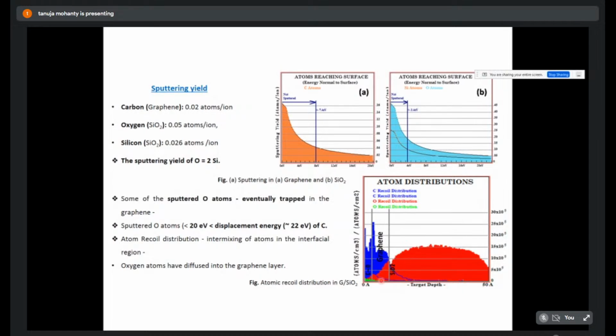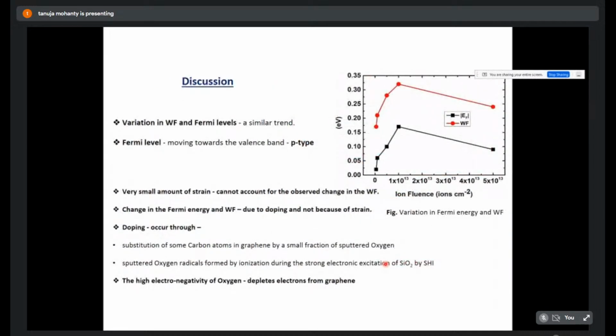So what we expect, that there is doping, means what? The graphene is deposited as single-layer graphene on a silicon dioxide substrate, and the range is very high. Some of the oxygen atoms here are getting inside it. So that is the oxygen recoil distribution that is getting penetrated in the graphene. That creates one type of doping in the graphene. So P-type doping is occurring in the graphene.